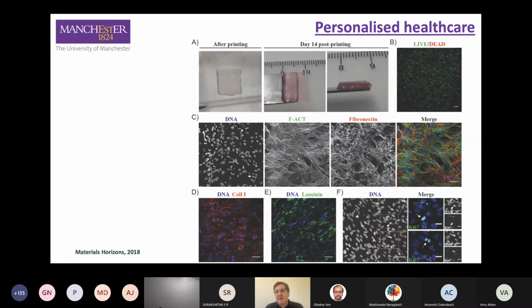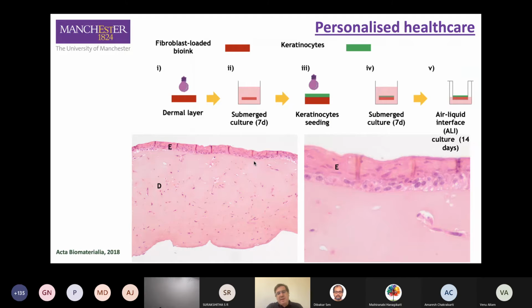We ran a couple of tests showing that cells were able to survive, and these results are from 14 days post-printing. So cells were alive and they were creating their own matrix, producing, for example, collagen and other proteins. And then we developed a more complex structure. In this case, we print 2 layers of material, again containing different cells. We induce a stratification process to create the dermal and the epidermal layer.